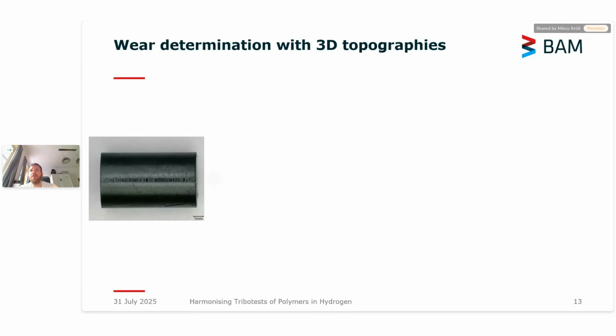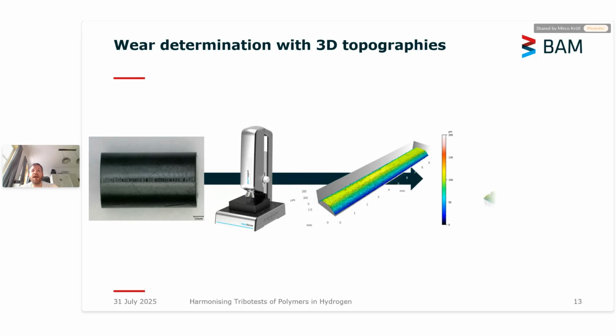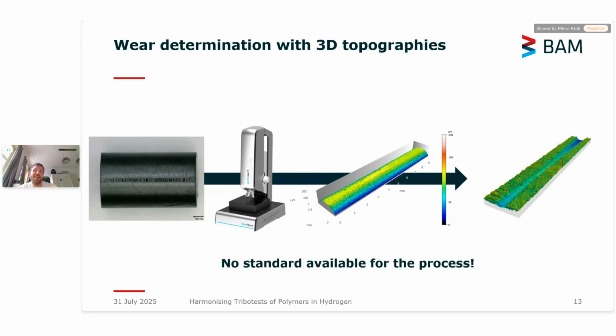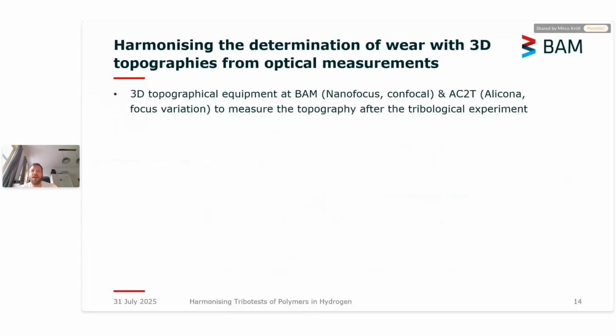We did that with a microscope, so that means we ended up with a 3D topography. So we have a confocal microscope, or any microscope, you get a topography of the sample, and then you need to manipulate this topography to actually determine the wear volume. The issue, and why we want to harmonize things, is that there's no standard available for this process. So at BAM we used the Nanofocus, which is a confocal microscope, as I just said. At AC2T, an Alicona was used, which is a focus variation